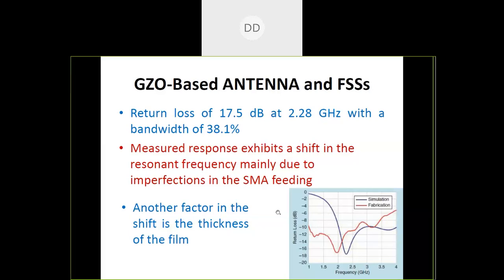So the shift, they analyzed that this is mainly due to the imperfection in the SMA feeding and due to the problem in controlling the thickness of the film. So these are very critical parameters in the case of optically transparent antennas using these TCOs, that we need to control the skin depth very precisely. Also, the feeding of the optically transparent antenna is a challenge because that will affect the response of the measured